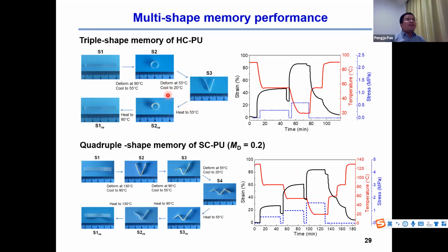For example, we can design a triple shape memory material from the homo-polyurethane. It was deformed at 90 degrees C and then cooled to 55 degrees C to fix the temporary shape. It was then deformed to the second temporary shape and fixed by cooling to room temperature. The sample can recover to the first temporary shape and then to the permanent shape upon heating.